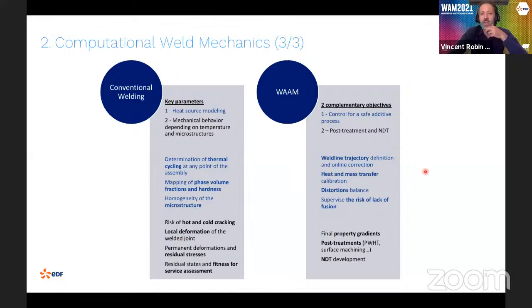And if we look at 3D printing using such welding processes, we have some other issues. The first one, which we have discussed also for powder metallurgy based processes, consists in optimizing the welding trajectory, but also calibrating the mass transfer and the heat transfer, which is very important to prevent some risk of lack of fusion, for instance. We also have to define the welding trajectory in order to prevent distortions. And finally, but not least, post-treatment and NDT are really an issue regarding this process in order to be able to qualify such a manufactured component.